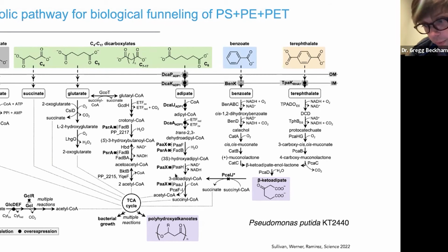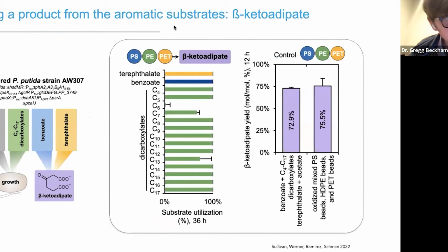The first one, we thought it would be fun to have basically, let's just produce one molecule only from the aromatic components. And then the second strain, we thought it would be fun to make a single molecule, PHAs, from all of the substrates. And so I'll show you the data on first, the aromatic substrates converted into a single product. And so now again, acetate and the DCAs go to growth, and the benzoate and terephthalate go to beta-ketoadipate. On a molar yield, starting with the aromatics alone, you can see we're able to reach 75% yield from the beads, essentially all in a mixed case. So that is pretty cool.